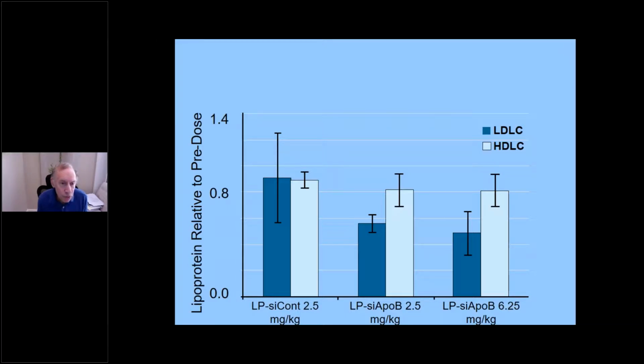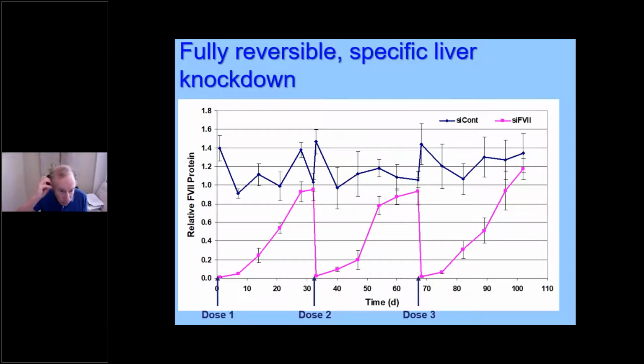And when you give these, it's fully reversible, and you can get very specific liver knockdown. One of the keys with Alnylam was that we use targeting approaches with GalNAc on the nanoparticle. And the next slide shows that over and over again, every month you could get knockdown. And then what Dan and I did is we said, well, could we take the very, very best lipid nanoparticles that we had, the best we call them lipidoids because they have a little bit different structures, and then make them even better.